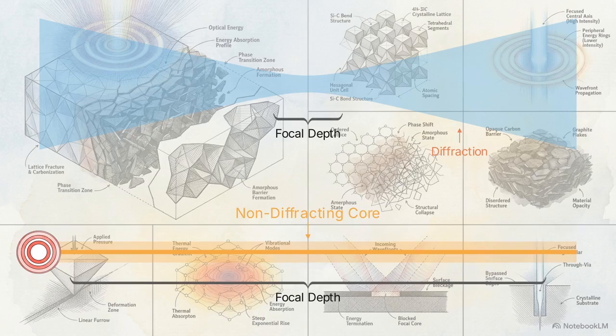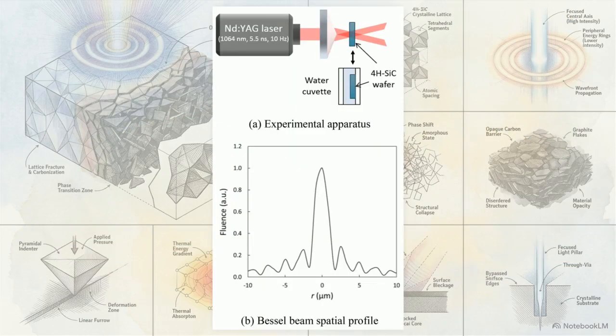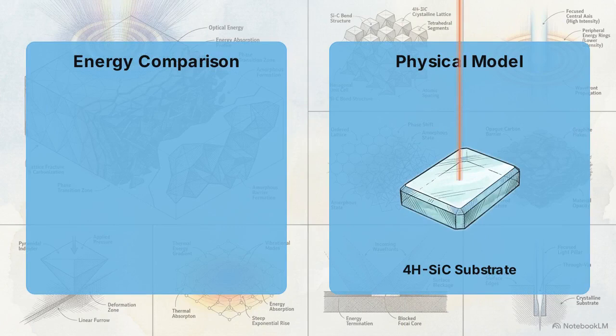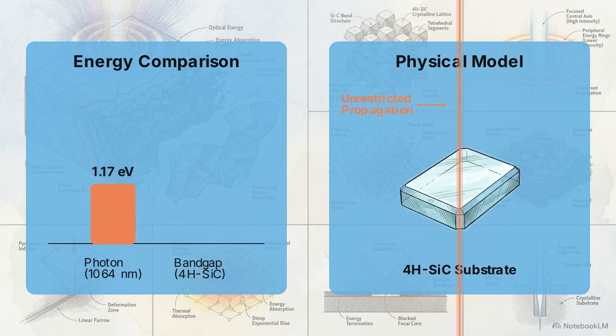This graph maps the spatial profile of the Bessel beam. There is a high-intensity central peak at 0 micrometers, surrounded by undulating side lobes that spread outward. 4H SiC is transparent to the 1064 nanometer near-infrared wavelength used here. The laser's 1.17 electron-volt photon energy is far below the material's 3.23 electron-volt bandgap, which should allow the light to propagate deep into the substrate.